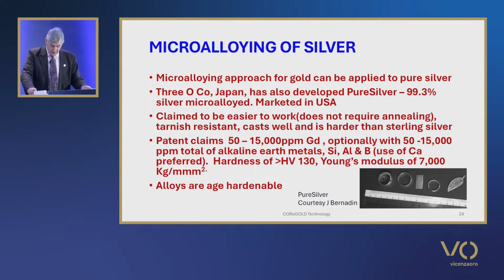The patent covers microalloyed gold, silver, palladium and platinum materials. In the case of silver, an alloy of at least 80% silver is claimed, containing the rare earth gadolinium in the range of 50 to 15,000 parts per million, with optional further additions of alkaline earth metals, silicon, aluminium and boron in the range of 50 to 15,000 parts per million in total, with hardness values of 130 Vickers or higher and a Young's modulus of not less than 7,000 kilograms per square millimetre.